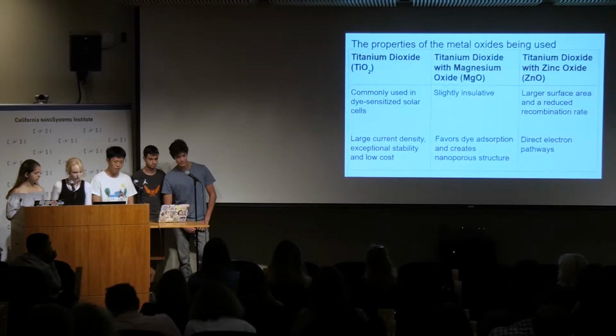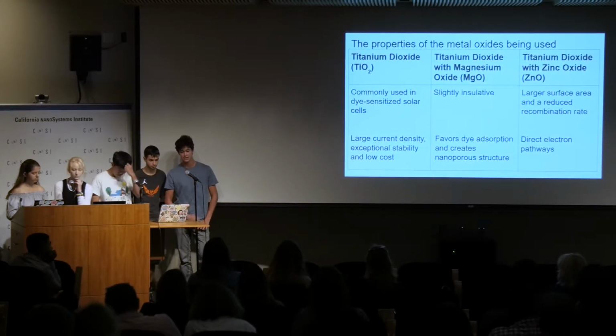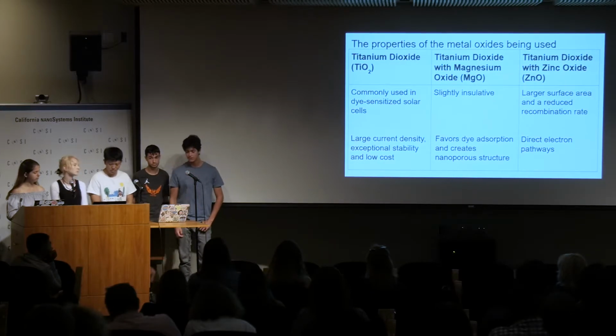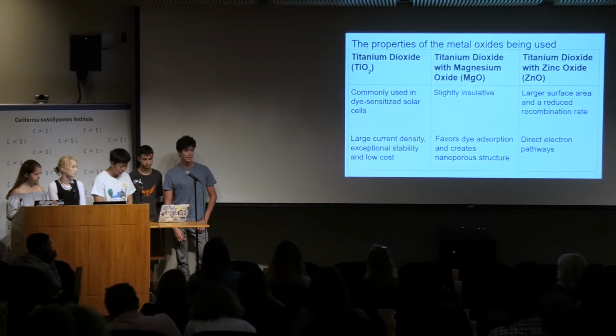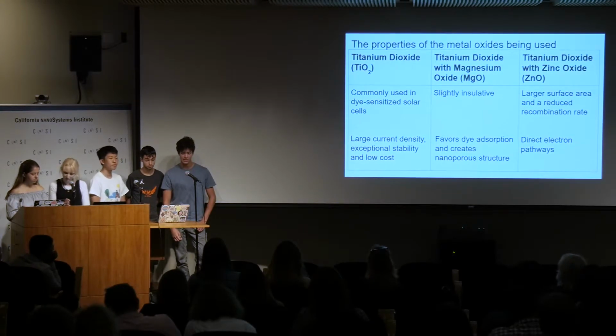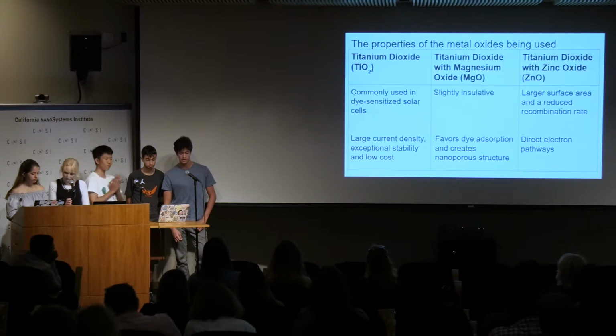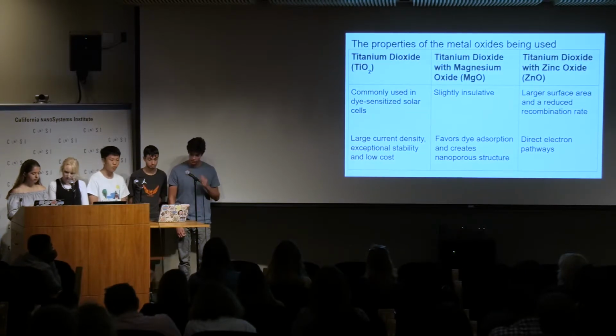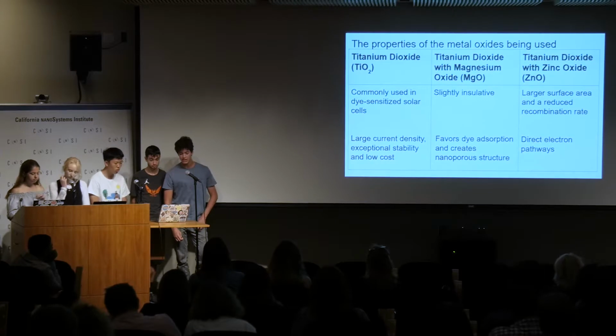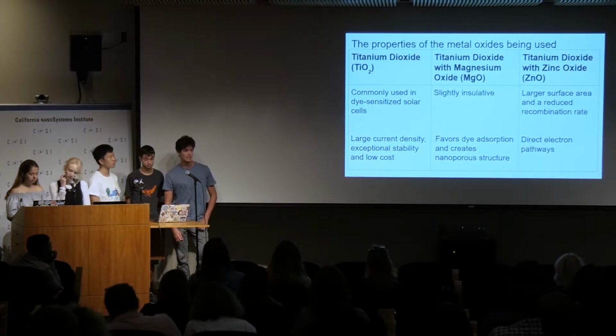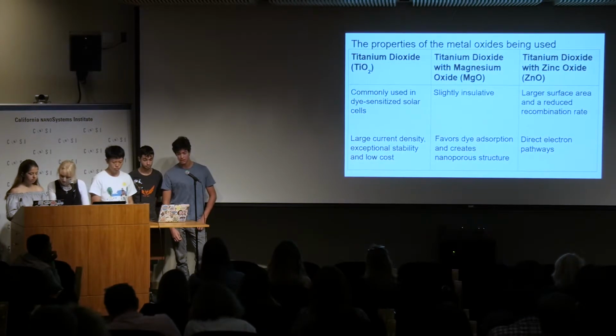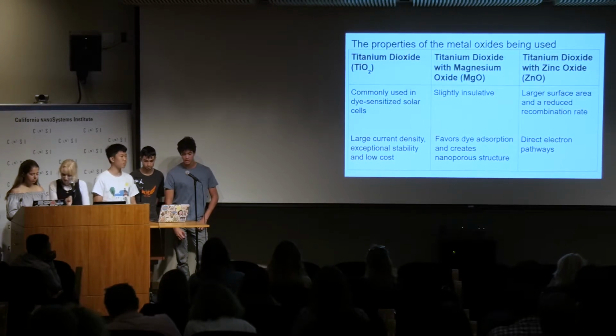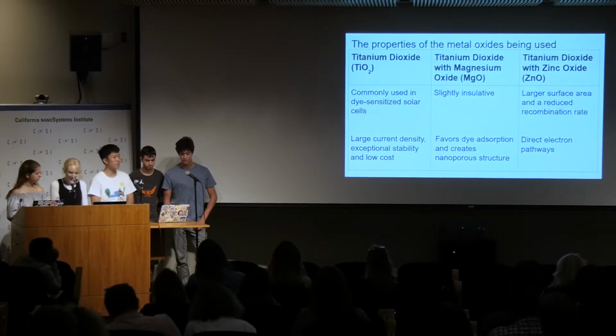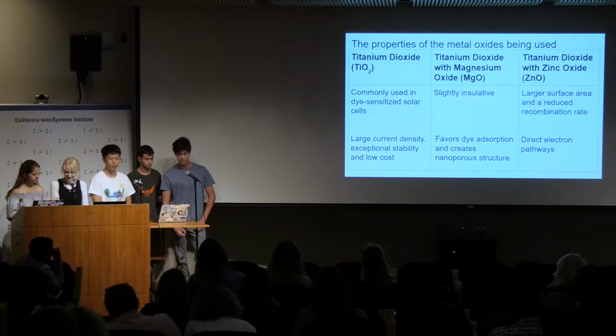So in our experiment, we tested several different metal oxides, the first being titanium dioxide, also known as TiO2, and it's commonly used in dye-sensitized solar cells. Its large current density, exceptional stability, and low cost make it an ideal material. And the next metal oxide that we tested was magnesium oxide. And magnesium oxide is slightly insulative, which gives it some different properties. It also has a nanopore structure, which increases dye adsorption.